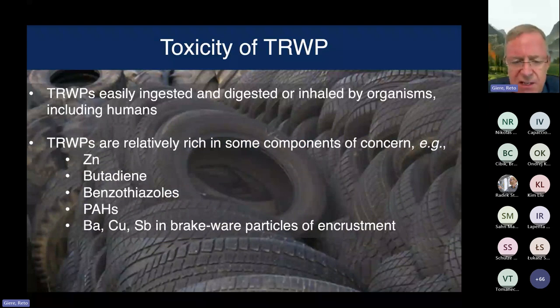The second concern is that these tire and road wear particles contain chemicals that may have potential health effects. I just list a few here. Zinc, you probably know zinc is an important vulcanizing agent that is added. Zinc in high concentrations is toxic. The second component, butadiene, is obviously a very important component of tires, a major component, and it has recently been classified as carcinogenic to humans. The next component, benzothiazoles, these are special organic components that are added to tires for various purposes, and there are quite a few different types that are added. And these benzothiazoles are biocides, and they're potentially aquatoxins and also mutagenic.